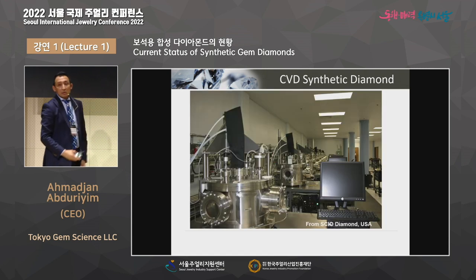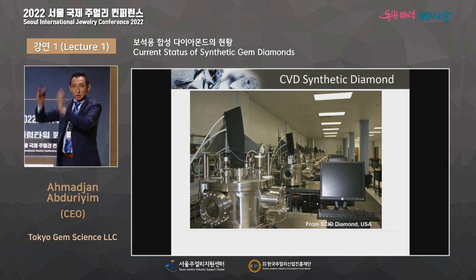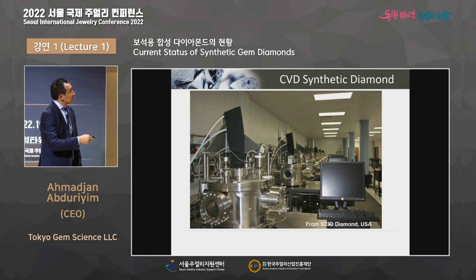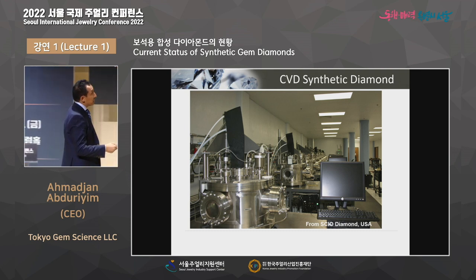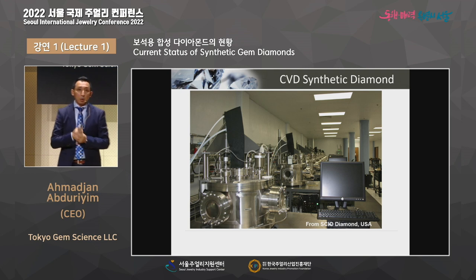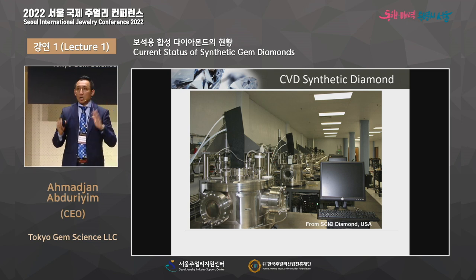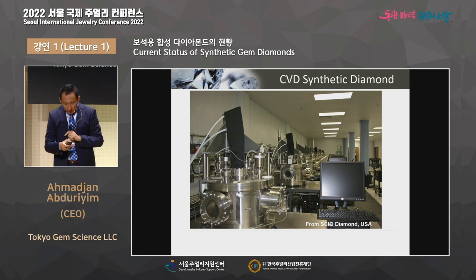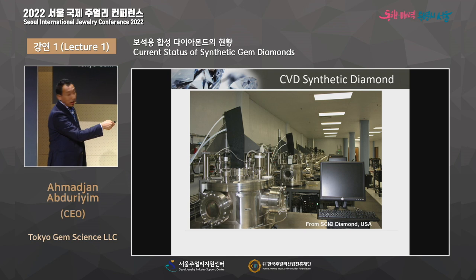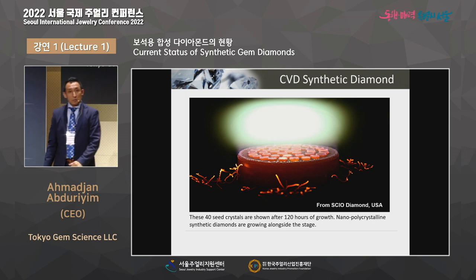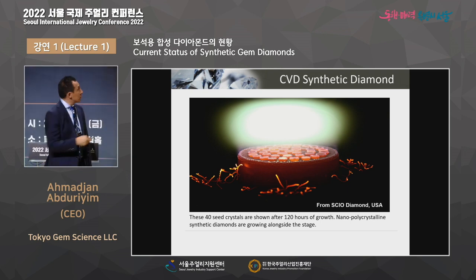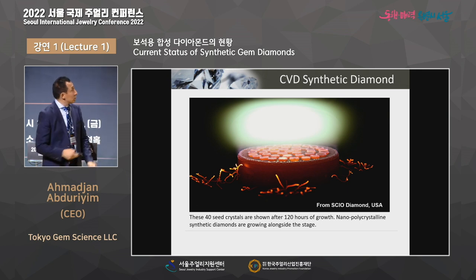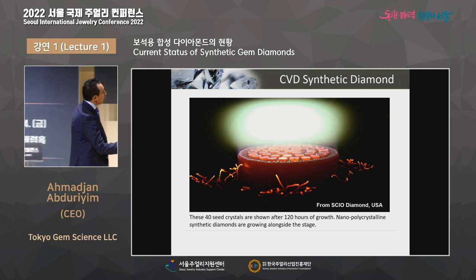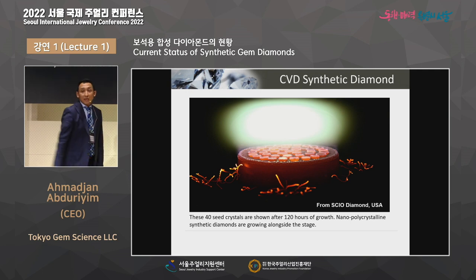And you will see a lot of instruments like this. You just make a lot of instruments, made much smaller. This is a picture from SCIO. It's a former Apollo diamond. Apollo diamond is a pioneer to create the CVD gem quality diamond in the USA. And this is the inside. You can see there are countless CVD instruments that create synthetic diamond. And look at the inside. They can use more than 40 seeds to create 40 crystals, even up to 50. So in 5 days, you will get 40 crystals like this.